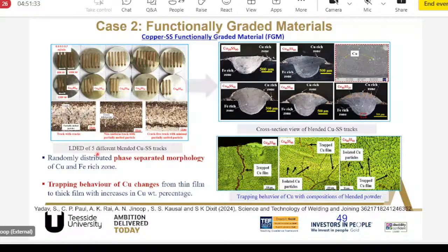Then we can see how the copper and stainless steel gradation has happened, and we can see how the copper particles are getting distributed in that matrix. And we could observe a lot of cracking in this particular case because these two materials don't go together. They don't work well together. So we can see phase separated morphology in copper and iron rich zones. Trapping behavior is seen. We can see the trapped copper films, and it increases with increase in the copper percentage.